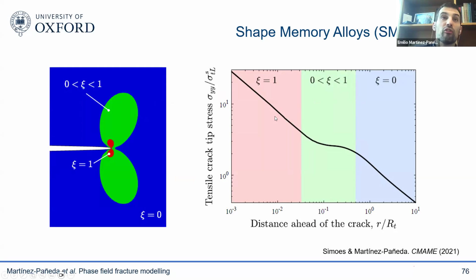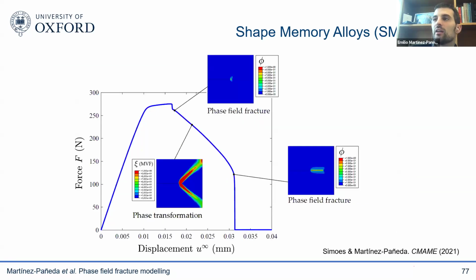So what we did was to develop the first formulation of phase field for fracture and fatigue in shape memory alloys. And that allows you to capture the main features that you see. One of the main features is toughening due to this phase transformation. It's a little bit like plasticity in a way. So if we go back to that classic benchmark that I showed you before of the square plate and the crack, you can see that the force displacement curve goes up, but then instead of dropping sharply, you still sustain some load, you get stable crack growth due to these phase transformations. In a way, it's a little bit like plasticity.